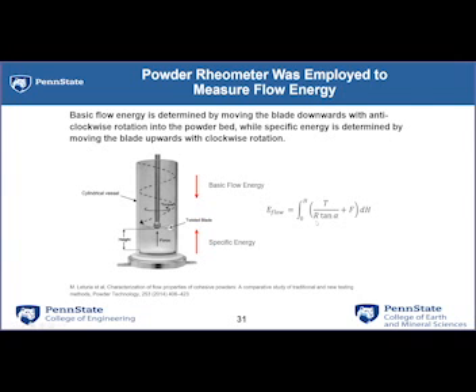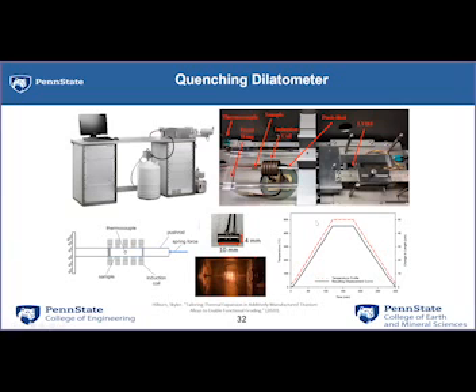As we move on here, our quenching dilatometer is another capability. And I always like to show this because this tells us a little bit more, not only of phase transformations, but of starting to understand a little better and doing very high resolution measurements of thermal expansion. We're seeing, particularly in the additive field, as we additively manufacture different components, their coefficients of thermal expansion are not well defined. And so we can take small specimens, and these can originate from a powder, wrought, whatever type of material you want, heat them up at very specific rates and cool them at very specific rates.